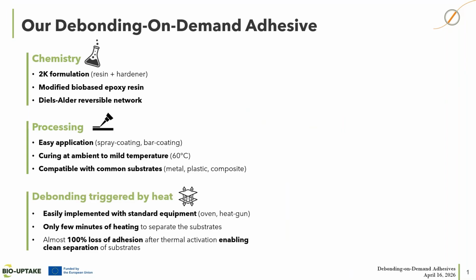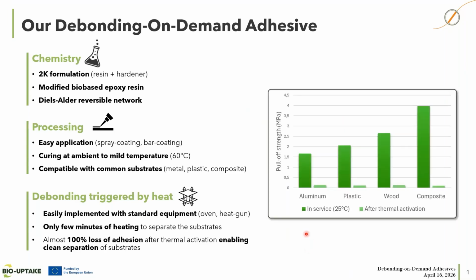So when debonding is needed, a simple heating using, for example, an oven or a heat gun triggers the process. And within minutes, we can observe almost complete loss of adhesion, which allows the clean separation with minimal residue. So this is illustrated on this graph, which displays the adhesion strengths on various substrates at ambient temperature. So we can see here that the adhesion strength is quite high, and after thermal activation, we have a complete loss of adhesion.